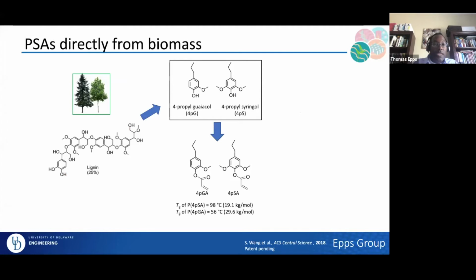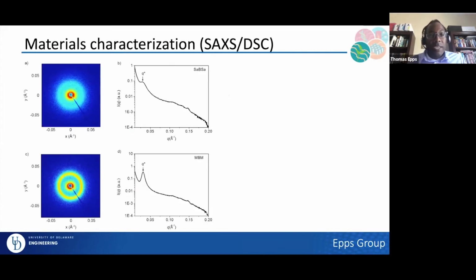So we can take them, we can actually, if we want to, extract the various components. We had these two major components, so the 4-propyl guaiacol, so 1 methoxy, and the 4-propyl syringol, so in this case 2 methoxys. We could actually polymerize, or in this case do acrylate functionality instead of methacrylate. Polymerize, for example, homopolymers if we extracted some, just to get an understanding of what the glass transition temperatures would be. But I will say for going forward, we actually just used the mixtures because they had the exact properties that we needed. So we can take that block copolymer, again, made from the mixture of biomass.